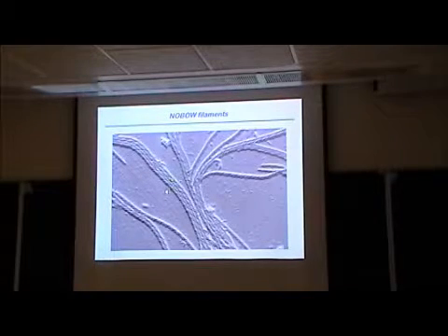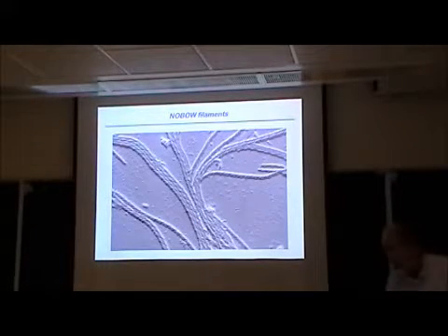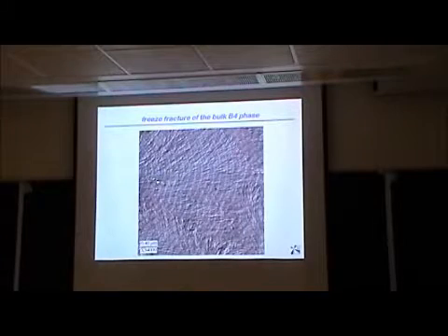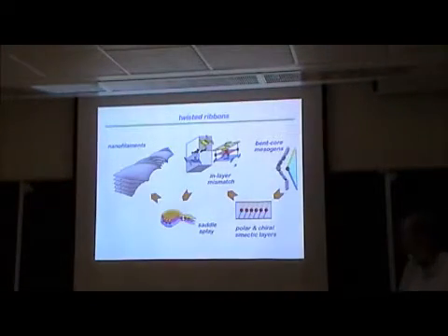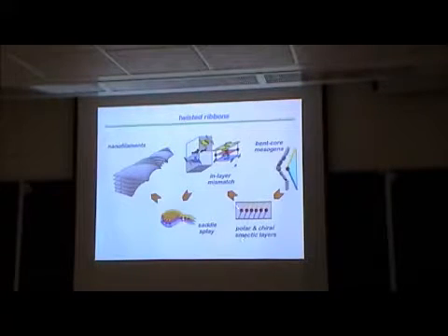So this is a phase that's made up of filaments. Okay, and in a neat sample, these filaments are along these lines here. These filaments pack together to fill space. The reason the filaments form is that these tilted polar layers have a very strong tendency to have saddle splay curvature. They don't like to be flat.